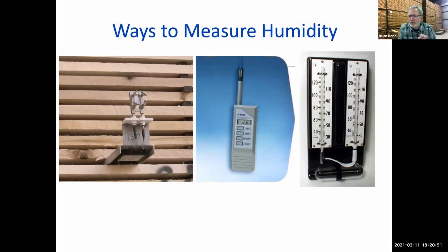So when you're drying lumber, it's important to be able to measure the temperature, be able to measure the moisture content, but also be able to measure the relative humidity. And these are just some tools that you can use to measure the relative humidity. This is a little wafer used in a commercial drying operation. This is pretty much the archaic, simplest way to do it, which is a wet bulb and a dry bulb. Basically, you have a thermometer here that measures the air temperature. You have a thermometer that has a wick on it. And so this wick is supposed to be wet.